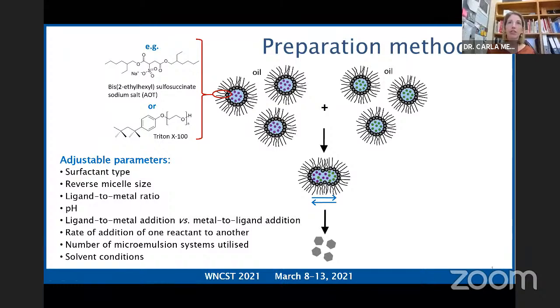And in that way, we can effectively control the concentration of ligand and metal ion throughout the course of the reaction. We can control the number of microemulsion systems used. So after we mix the two microemulsions, we could add in a third microemulsion that contains either an acid or base, for instance, to control the pH or to change the pH, or another microemulsion that contains yet another metal or another ligand, so that we can start forming hierarchical structures or bimetallic MOF structures. And we can change the solvent conditions, et cetera.